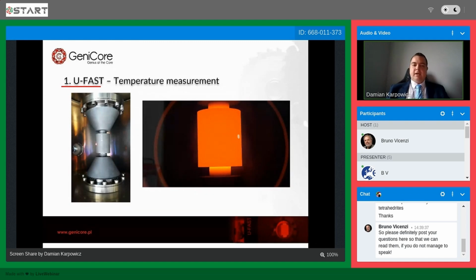I think it is worth considering that temperature control is very, very important in SPS technology, because we need to watch out not to go too high with the temperature. But in this case, in the GeniCore solution, we are mostly using pyrometers. When we make precise and accurate measurements with thermocouples first, the customer or user can then just use the pyrometers. So in this case, we are using the axial pyrometer, which is in the top stamp, the top electrode of the device, and also two side pyrometers, which combined allow us to cover the full range of temperature, starting from room temperature up to 2500 Celsius degrees.